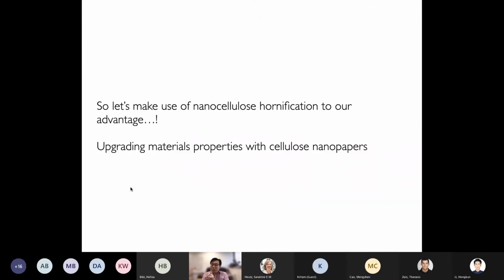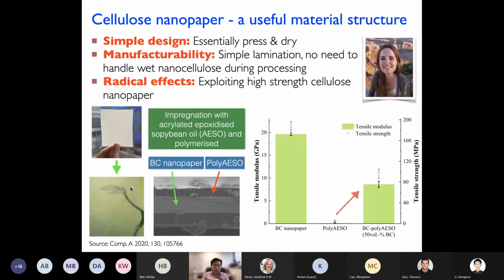But what we can do is to utilize nanocellulose hornification to our advantage by using the nanopaper as the reinforcement for our polymers. So this is the thesis of Alba, who actually investigated nanopaper as a useful building block. What she essentially did here is to take that dry nanopaper. So you take the wet gel, you dry them easily by pressing and drying. You can do this at home with a simple panini press or even a simple iron. You can do that. And you then laminate this paper with an epoxy.